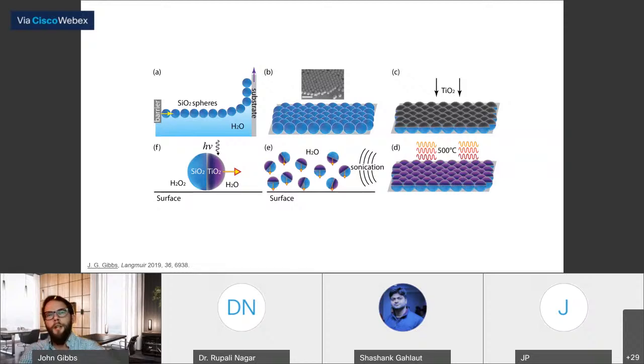However, we want to take advantage of GLAD, and with GLAD, you really want to have a patterning across the entire substrate. So the next step would be to just deposit titanium dioxide directly on top of the spheres. Then we have an annealing process just to get them into the correct crystal phase, the anatase crystal phase. We use an ultrasonicator to remove them from the surface. Once they're in a solution of hydrogen peroxide, we can use the activating light, the ultraviolet light from a fluorescence microscope, to get these things to start moving around.